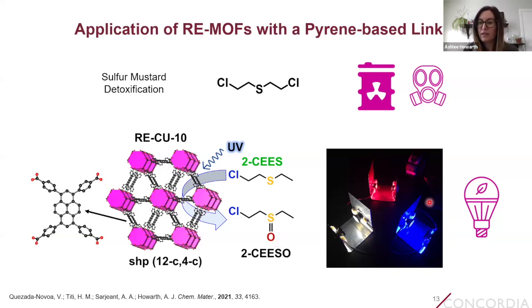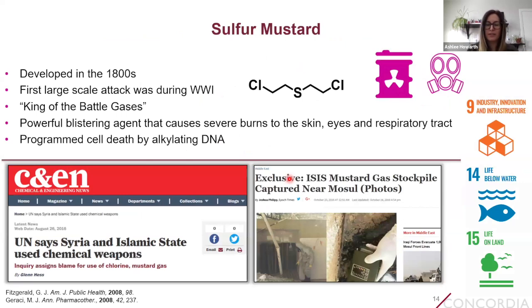And we do this using these home-built UV or other colored LED setups, where we use these to irradiate the MOF, especially the photosensitizer, the pyrene, generate the singlet oxygen, and do this selective oxidation chemistry. Now, in our labs at Concordia, we of course don't use the real chemical warfare agent mustard gas, but instead we use a simulant called 2-chloroethyl ethyl sulfide, which has similar reactivity but is much safer and easier to handle. And so before I show you the results, I should just briefly explain why are we interested in the detoxification of sulfur mustard in the first place. So first some background, I guess.